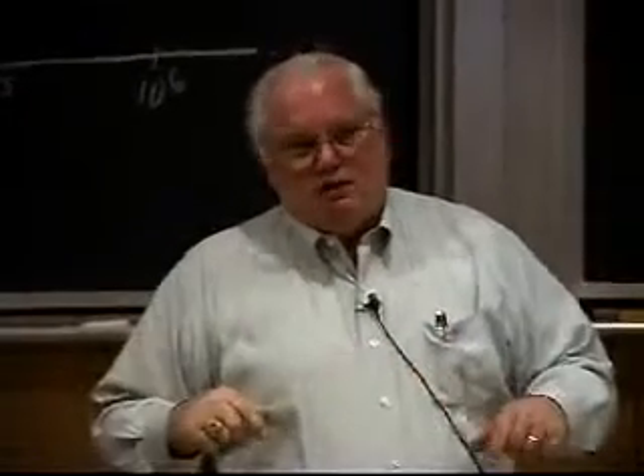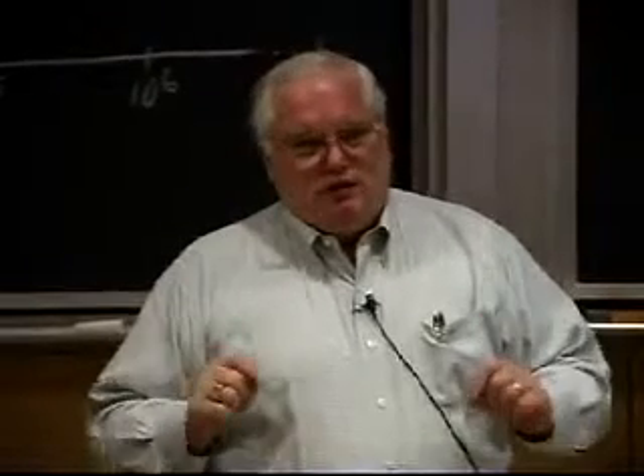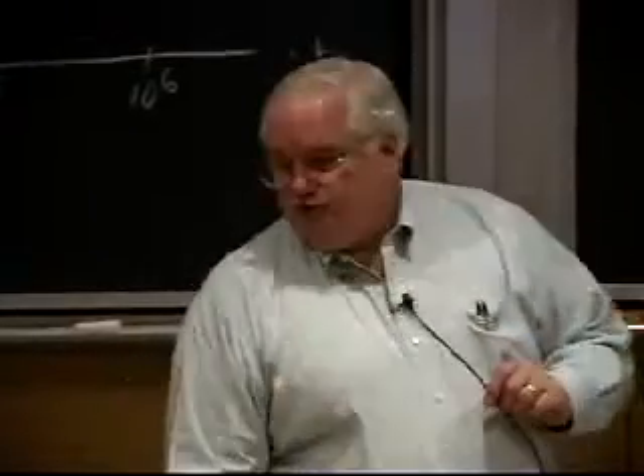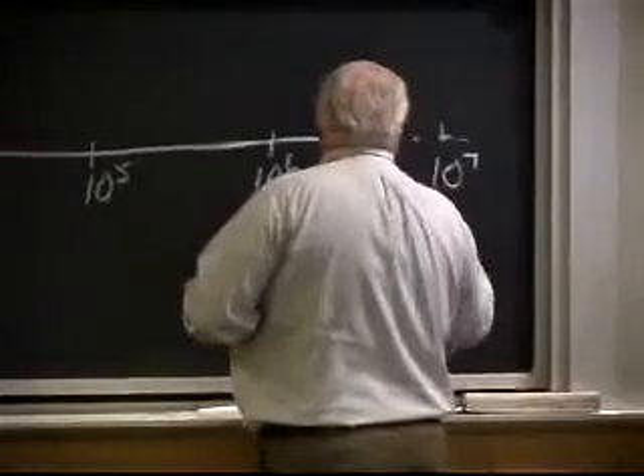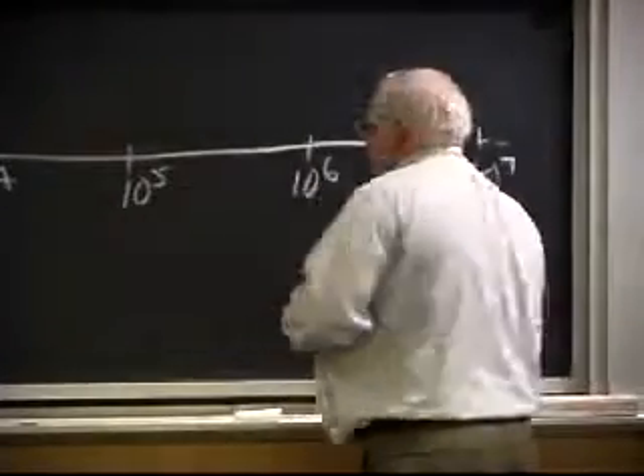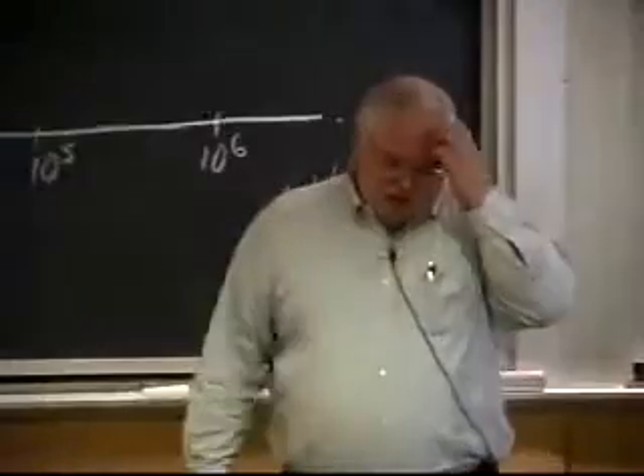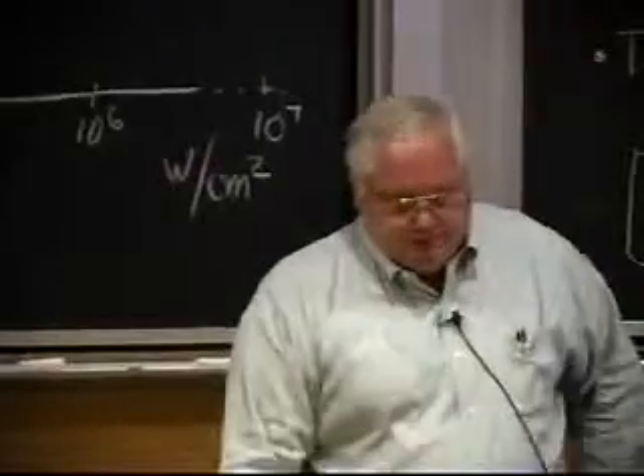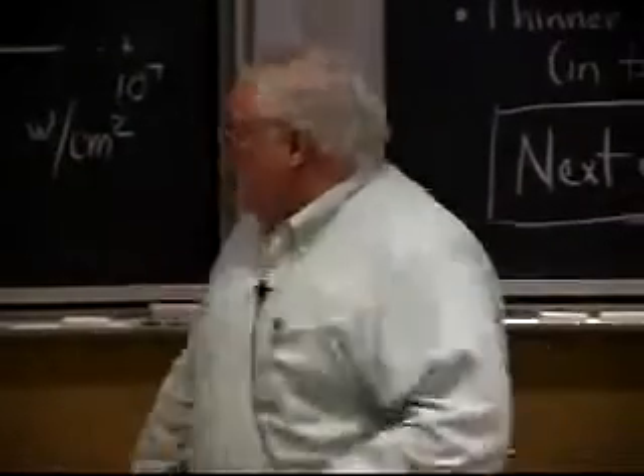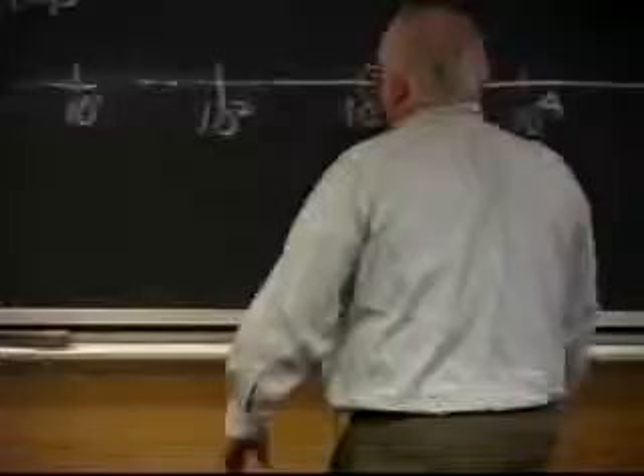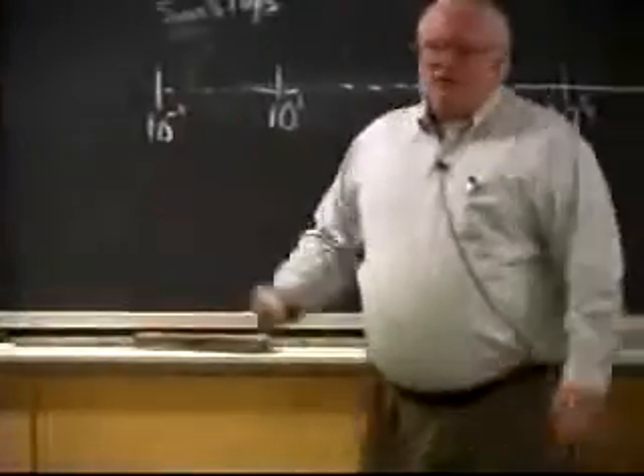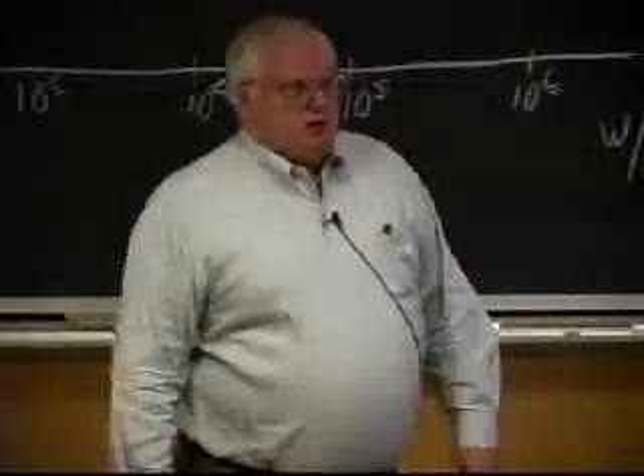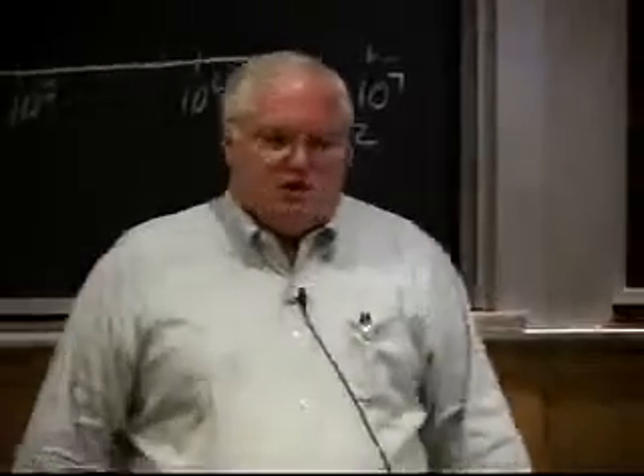In fusion welding, we're interested in heating the material to melt it. And in general, not always, but in most cases, we're doing surface heating. And for surface heating, it's useful to think of things in terms of watts per square centimeter. This is a log scale of watts per square centimeter impinging on the surface. The sun's rays are something on the order of a few tenths of a watt per square centimeter on a nice sunny day out.